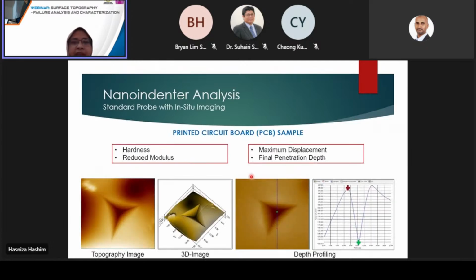For the next testing, we did the indentation on the PCB boards. This is what I want to show you, the capability of the in situ imaging. It doesn't just give the topography images, but it also can give 3D images, so that we can get a better understanding of the indentation and also the conditions of the surface after the indentation, whether there is some fracture. And also there's a profiler that we can use to measure the vertical and horizontal of the indentations.